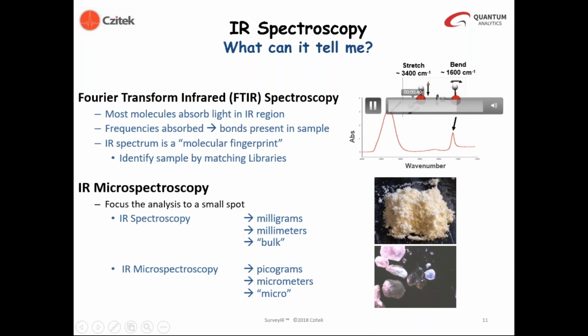And in this example, we're showing a couple of the vibrational modes of water, H2O, where they appear in the infrared spectrum and the vibrations that they're due to. So around 3,400 wave numbers is the oxygen-hydrogen stretching mode, and around 1640 wave numbers is the oxygen-hydrogen symmetric bending mode. So molecules with more atoms will have much more complex spectra than water, but that complexity in the spectra